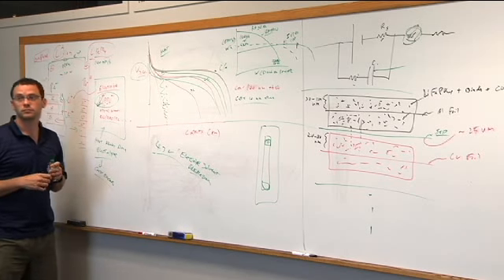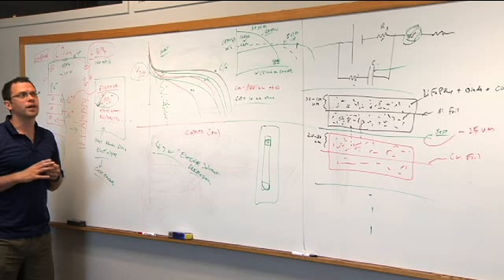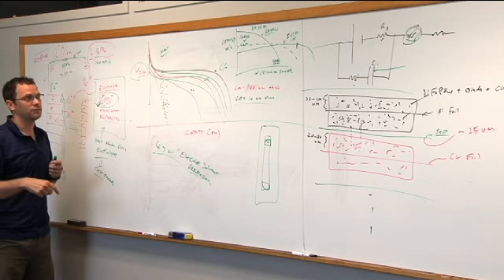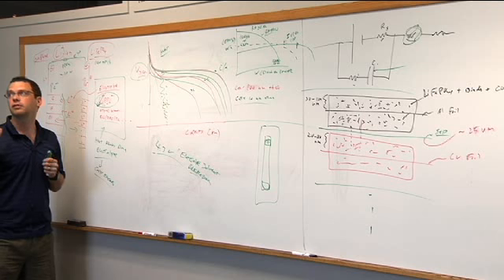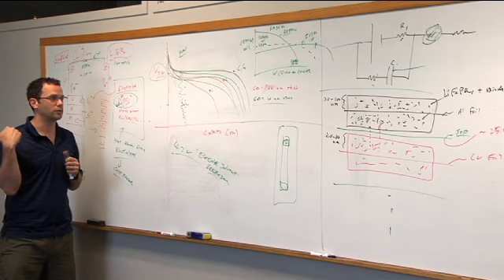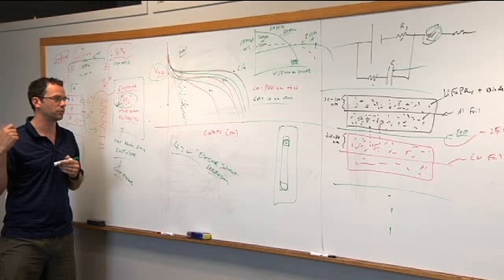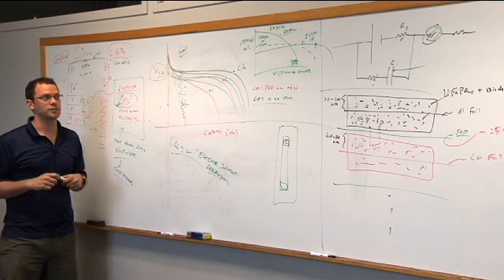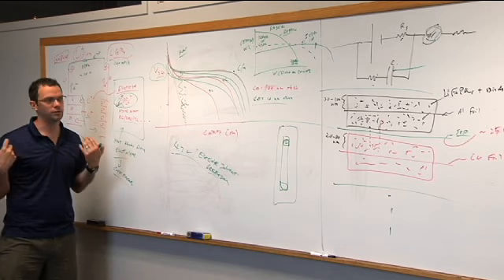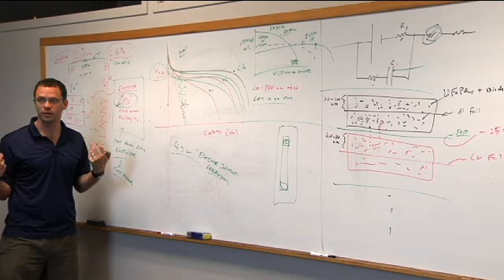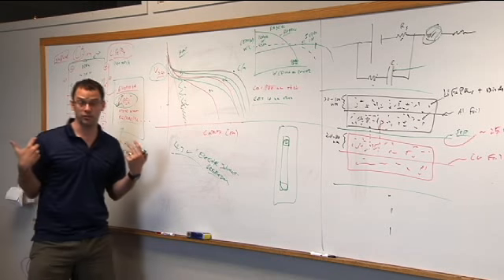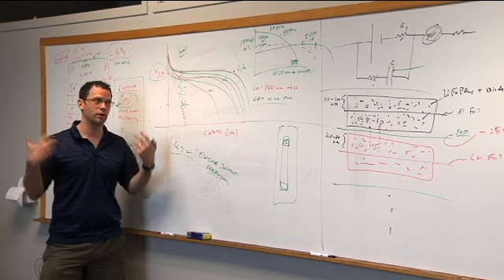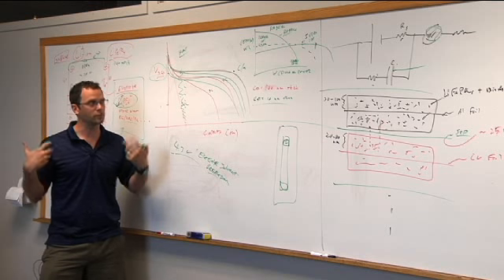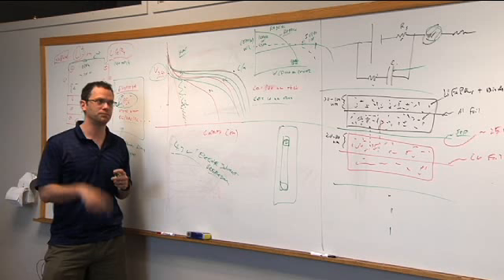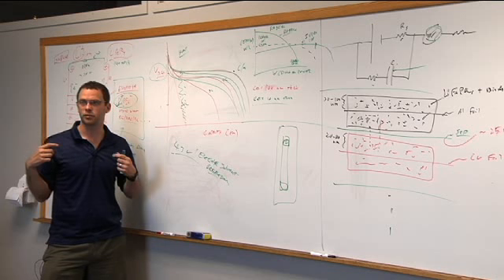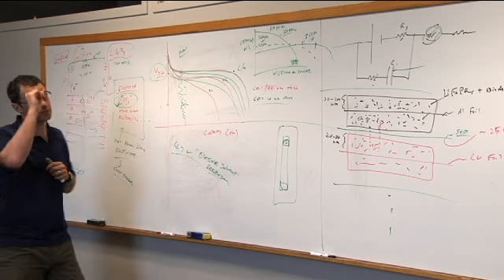So if you go below like minus 20, are you damaging something? Or no, you don't damage it. You can just freeze it. In fact, we did this, or they did it under my suggestion for the Lunar X program. There were some undergrads working with Red, and they took some lithium iron phosphate batteries and froze them in liquid nitrogen. The question was, under the 14-day lunar nighttime period, what happens to these batteries, if other things can survive over this time without any sort of isotope heating or anything? They froze them in liquid nitrogen, took them back out, thawed them out, and they ran fine, right? It's okay. You can freeze them, no big deal.